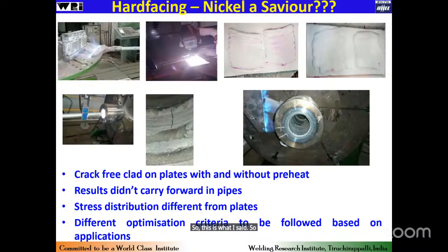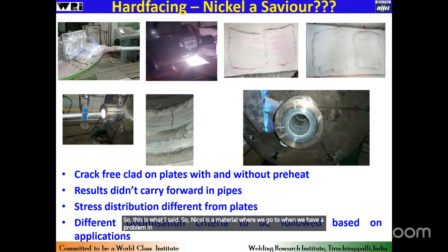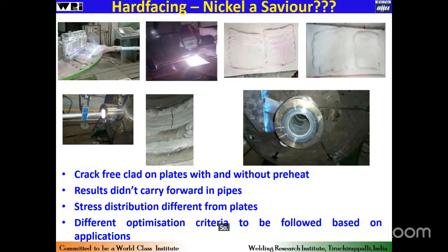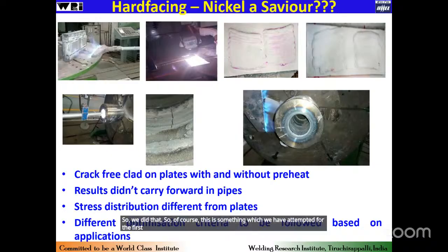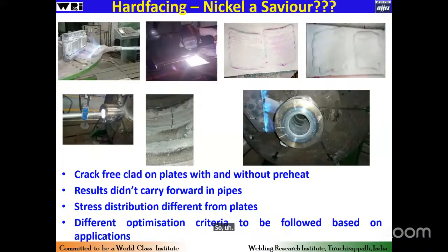So this is what I said. Nickel is a material we go to when we have a problem in weld fabrication. We thought it was going to be simple to do the hard facing on a nickel based material, so we did that. Of course, this is something we have attempted for the first time, where the internal deposition using plasma arc welding to improve the wear resistance of the nickel based superalloy. So here we have developed the process.